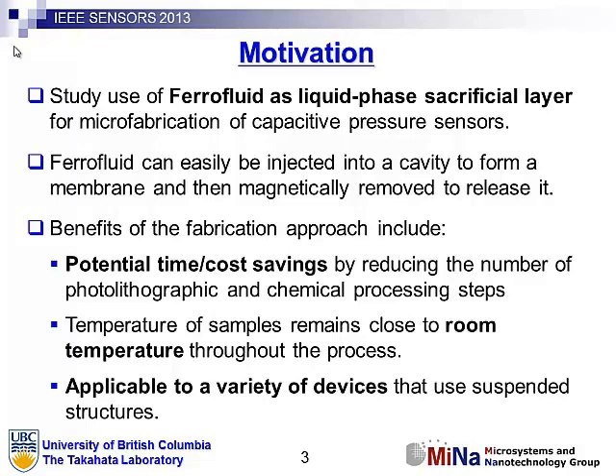And so because stainless steel is rougher than silicon and also has a much higher thermal expansion, we wanted a process that could work at lower temperatures and on a rougher surface. And this was one of the attempts that a student in our lab tried, was trying ferrofluid as a sacrificial layer. I'll show the fabrication process in the next slide. But the benefits of this, as I mentioned, are that it occurs at room temperature, and there were also no photolithography steps in this particular process. So in this case, it was time saving as well.